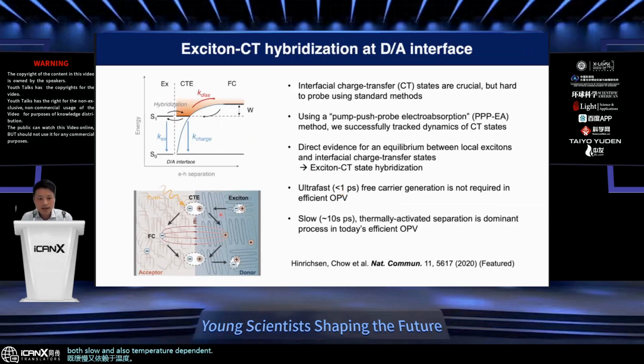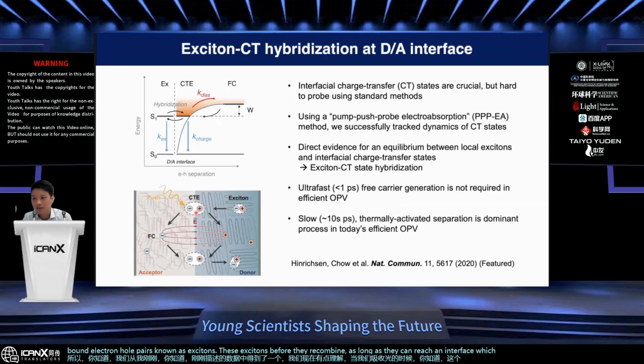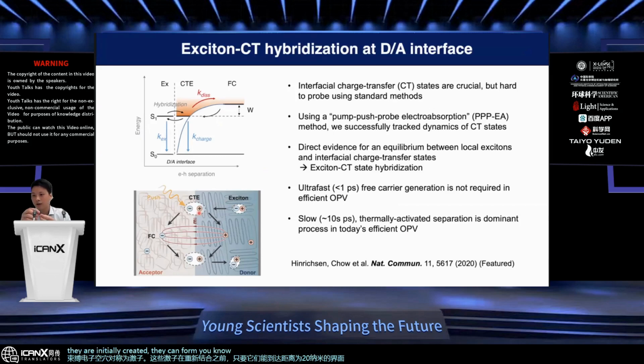From the data I just described, we now understand that upon light absorption, we create tightly bound electron-hole pairs known as excitons. Before they recombine, as long as these excitons can reach an interface, which is within 20 nanometers of where they are initially created, they can separate, and then further separate upon thermal activation into free electrons and holes.